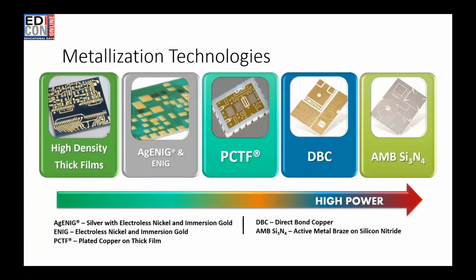The metallization technologies, as you can see on this spectrum here, go from low power to high power. Thick film circuits in general are operating at low power, low voltages, and currents. And there we can provide high density interconnects as well as high density circuits. The next one is what is called ENIG plating, and that involves silver or gold with electroless nickel and immersion gold. And the next one is PCTF, which stands for plated copper on thick film. What is done here is that we start with a substrate, we put a seed layer, which could be silver, and then we electroplate the copper. And this can typically be plated up to any thickness required. The most common is up to 5 mils.